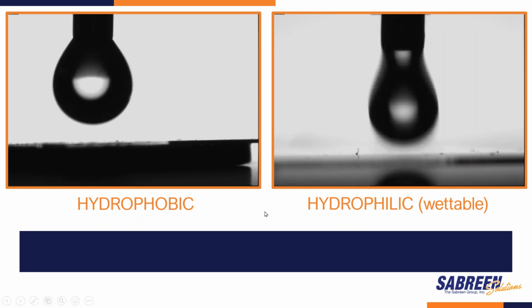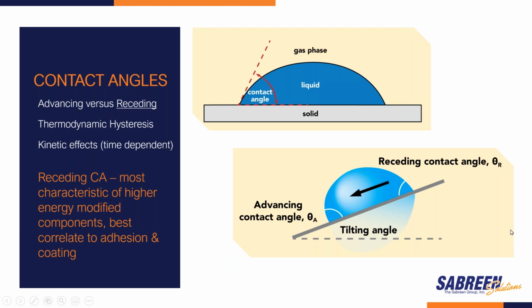Moving forward, let's examine contact angles and specifically a static contact angle on the top diagram. The contact angle formed by the solid surface and the tangent line to the upper surface at the end point is called the contact angle. The bubble or droplet shape is due to the molecular forces by which all liquids, through contraction of the surface, tend to form the contained volume into a shape having the least surface area. Contact angles are generally affected by changes in both surface chemistry and changes in topography.